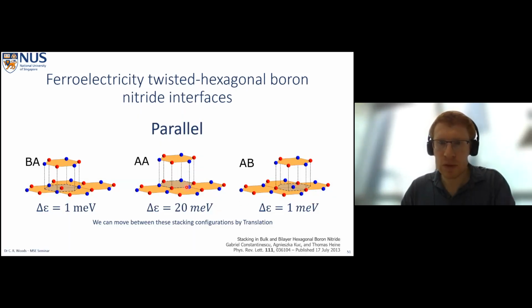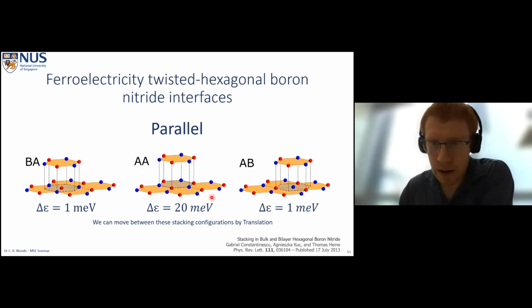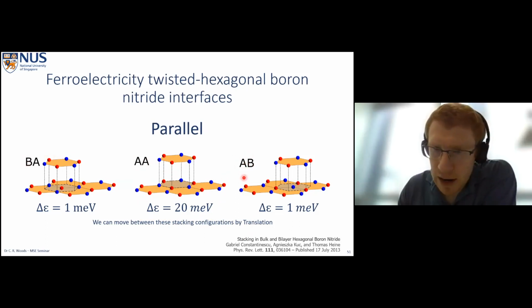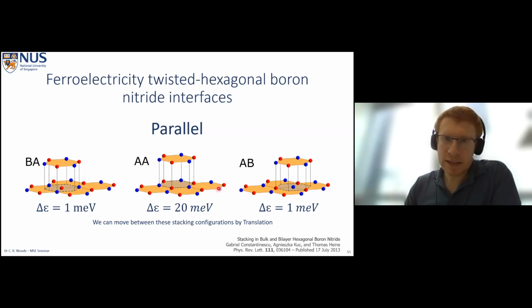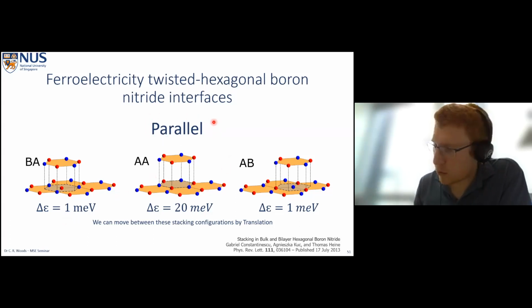So you can see now that relative to AA prime stacking, AA actually has very high energy. So it has low binding energy. This means this is very unfavorable for the parallel configuration. But whereas BA and AB prime were less favorable than the AA prime stacking, BA and AB are quite close in energy to the natural configuration for hexagonal boron nitride. So it will be interesting to see what happens when we can put our boron nitrides together in this parallel configuration. Interesting to see how the interface will restructure itself.